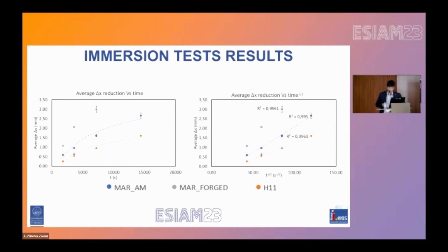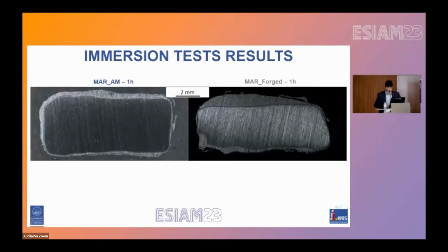On the right side, the average thickness loss was plotted against the square root of the immersion time in order to underline the linear relationship, which indicated that, as expected, the consumption of the steel sample is controlled by the diffusional process. Furthermore, as can be noted, the sample cross-section of the additive manufacturing maraging steel sample results in a more uniform dissolution as compared to the forged one.